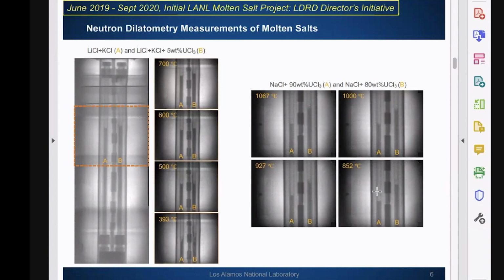We clean these up by taking baseline images from the dark field, so no neutrons, to fully assembled, and that helps us produce a clear image. Just to note, the lithium, potassium, uranium image at 393. So that's this one down here. You can see a little bit of interesting features there, not such a nice clean meniscus like I showed on the previous slide.